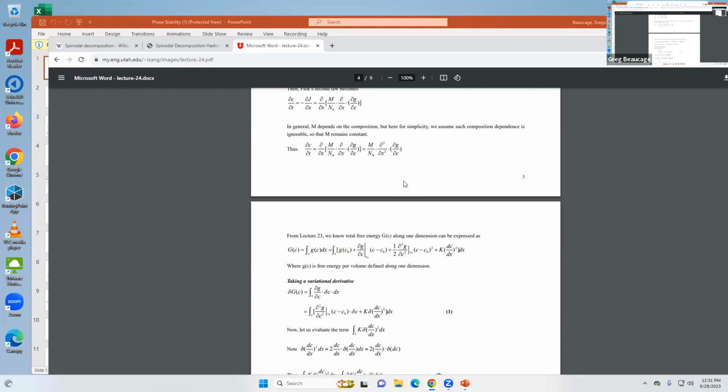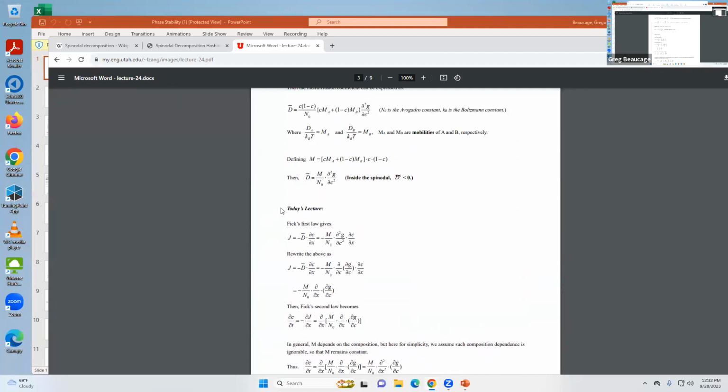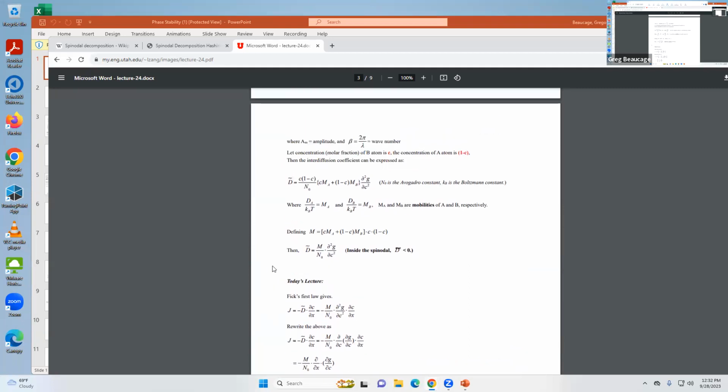And then the other big problem with it is, I don't know if I've emphasized it much, but basically people emphasize that there's a distinction between kinetics and thermodynamics, and you can't mix the two, right? The issue with spinodal is that you have to mix the two to get the answer, because it's basically determined by the balance between transport and this thermal driving force, and that leads to this phase size that you end up with. So you kind of have to cross a couple lines. And Cahn, most of the stuff cites this Cahn paper, and that stuff is indecipherable too.